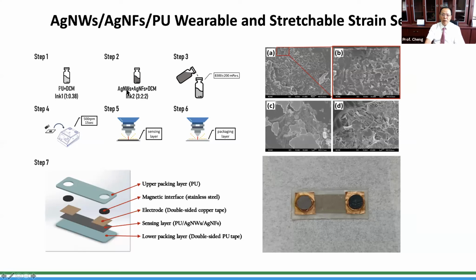With silver nanowire and the nanoflakes in the PU, we can assemble this sensing material by packaging it with these two PU tapes. And we also use a magnet as the electrode. Later on, we just use the magnet and then we can very easily extract the signal. In the SEM picture, you can see the nanoflakes and the silver nanowire very clearly.